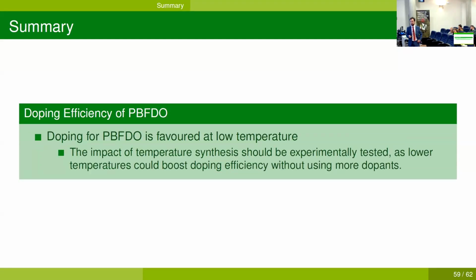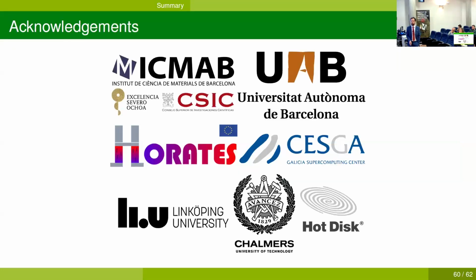We have also talked about how to optimize the doping reaction for PBFDO. We have found out that it is favored at low temperature, and that these findings suggest that the impact of synthesis temperature should be experimentally tested, since lower temperature could boost doping efficiency without using more dopants.